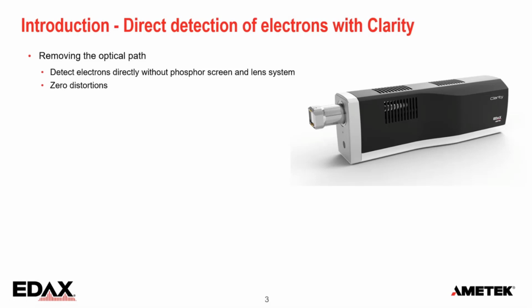And the detector that we use for that is the Clarity. And this was designed in the last years just to allow us to get to the next level of EBSD pattern collection. And one of the first requirements was to remove the optical path. So no phosphor screen, no lens system. So any distortion, anything that we would introduce during the transmission of the signal was taken out. So there's no distortion and everything we see on the detector really is coming from the sample.